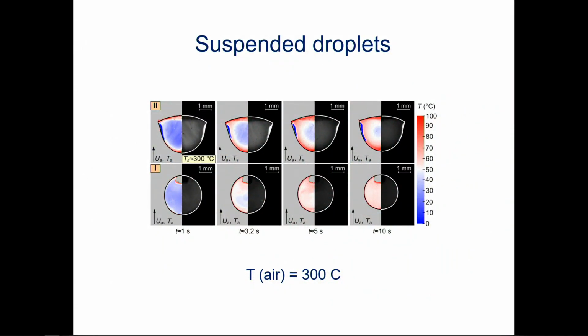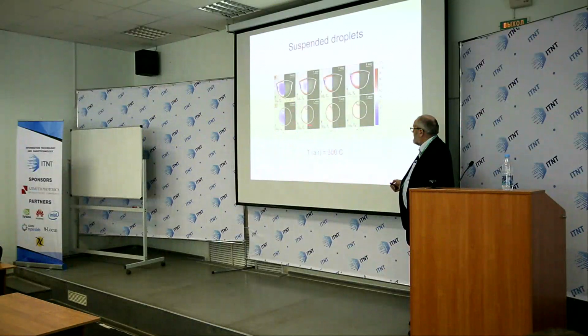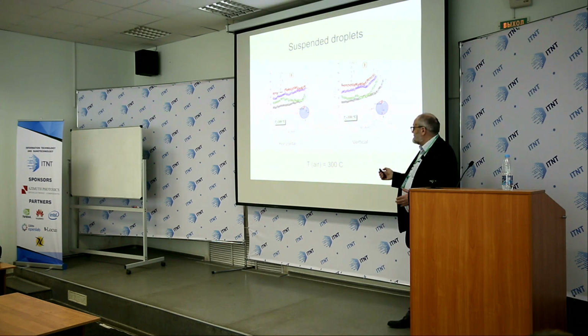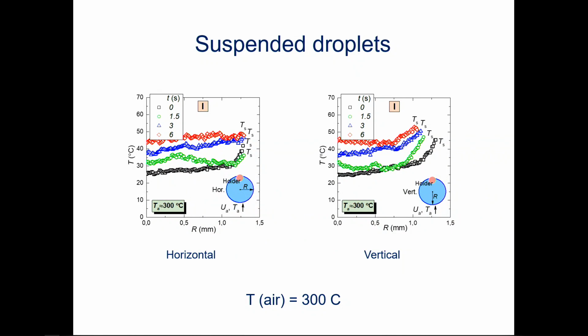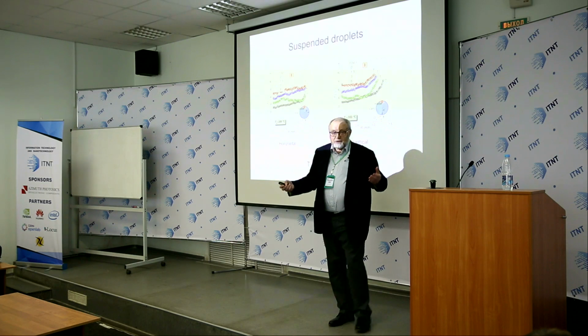Now, the experimental technique which they used allowed them to estimate the temperature distribution inside the droplet. And here you see some typical profiles at various cross sections and at various time instants. And the same distribution is presented on these plots, where we have the actual plots of the temperature inside the droplets versus the distance from the droplet center. And now the problem is how to model these phenomena, because these phenomena appear to be quite complex. You have a complex connection between the droplets and the rod.